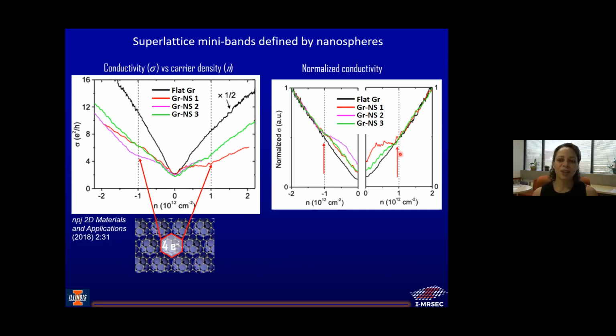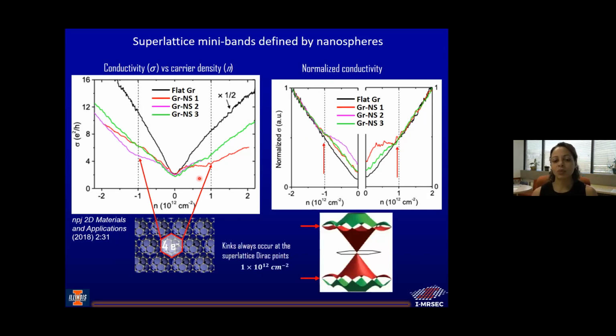Because that's our filling point for our nanospheres. And so the fact that we see these jumps exactly at 1 × 10^12 only for the graphene on nanospheres tells us that we're indeed measuring a superlattice due to the nanospheres, which is really nice because previously, when you took two different layers of materials, only certain materials worked. It really only worked for, say, graphene and boron nitride, because those are the only ones that were commensurate enough to create the superlattice effect. But now with the nanospheres, you can create any sort of superlattice in any sort of material. You just put it on top of the nanospheres, and you can see these sort of effects.